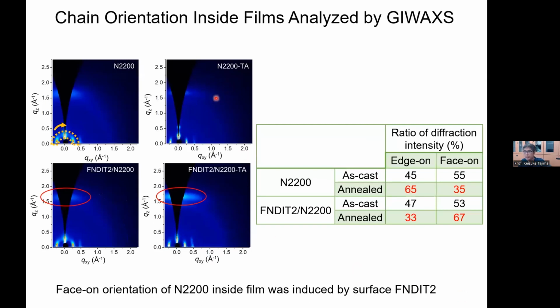After thermal annealing, we think we can affect the film structure. So here is the X-ray diffraction pattern. You can actually estimate how much of the polymer is edge-on and face-on by analyzing the diffraction of the polymer film. And here is the result in the table. It is edge-on rich in this ordinary polymer. But if you add the surface monolayer, after annealing, you get a higher component of face-on oriented polymer. And besides that, there's some diffraction here. You can see that it gets stronger, right? This is due to the pi-pi stacking, and this appears in the out-of-plane direction. That means that it's stacking this way. So even inside the film, it's getting a face-on rich component.